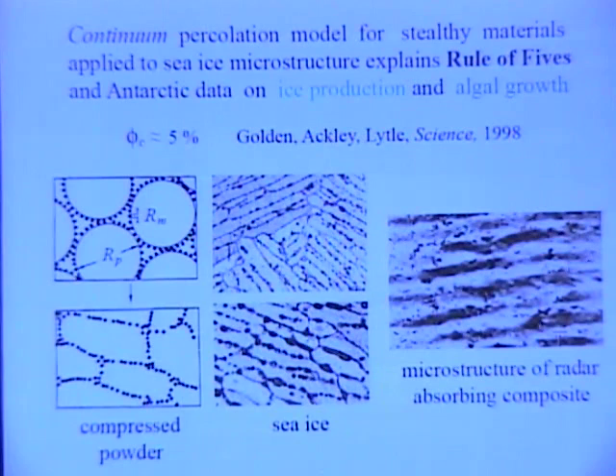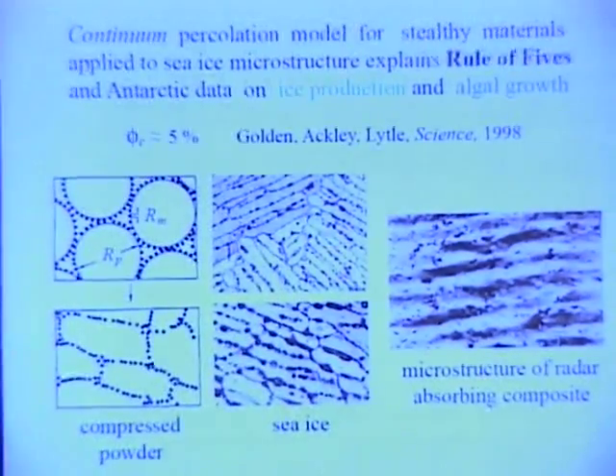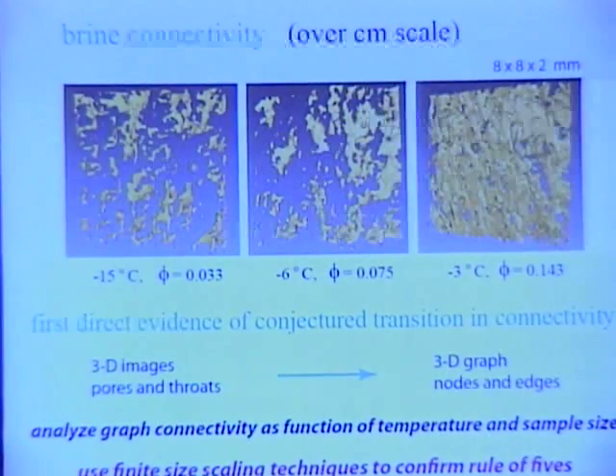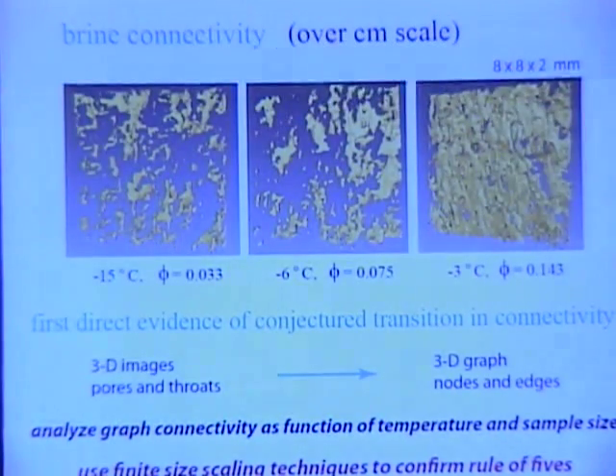Then they came up with this great idea in a paper in Nature back in the late 1960s, I think, or early 70s, that they could use big polymer spheres and little metal particles and then squash it together, and they could achieve the desired conductivity with much, much lower critical volume fractions. So I used their so-called compressed powder continuum percolation model, simply applied it to sea ice, and out popped the 5%, which explained all sorts of data on ice production and algal growth. It was conjecture at the time. I felt it in my gut that this was true, but I had no direct evidence that this was in fact going on. Now that we have our X-ray tomography, we can really show, yeah, it's right.